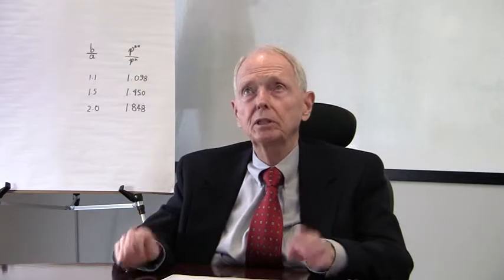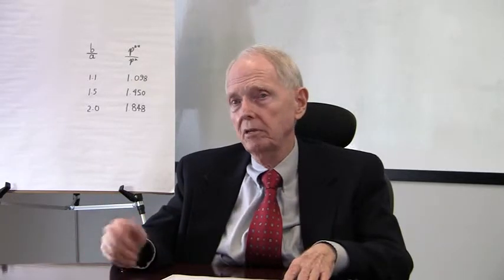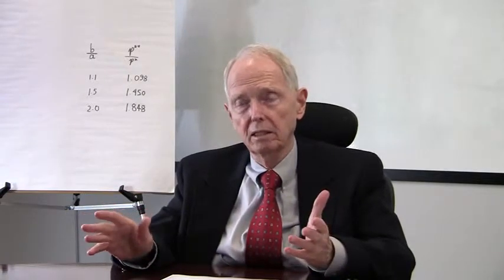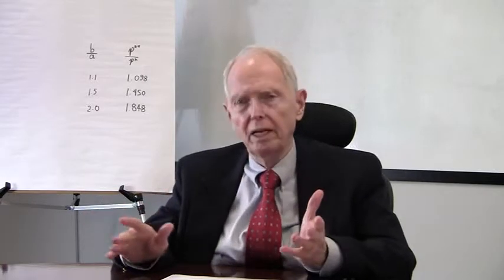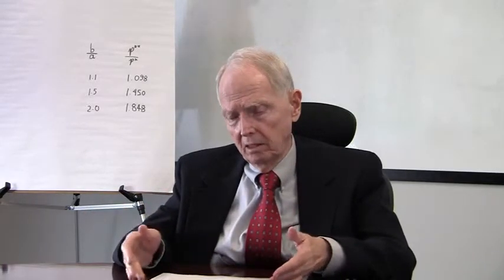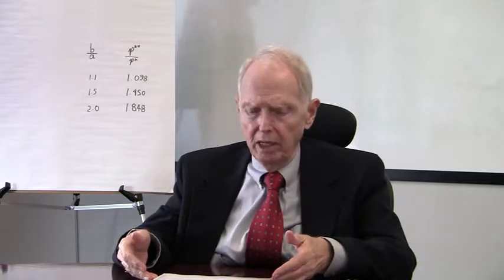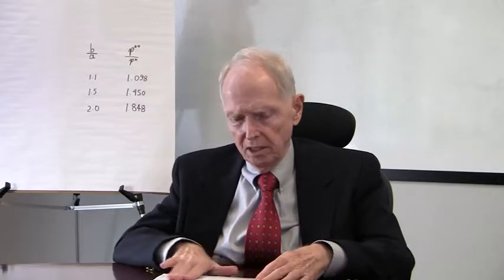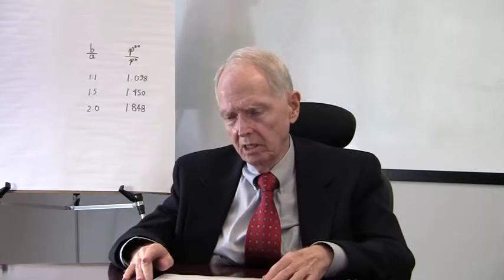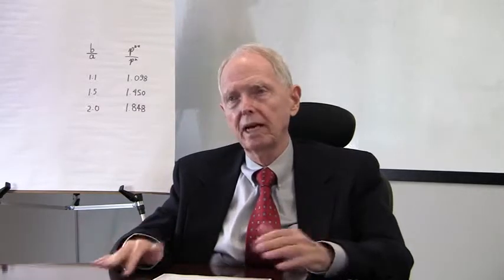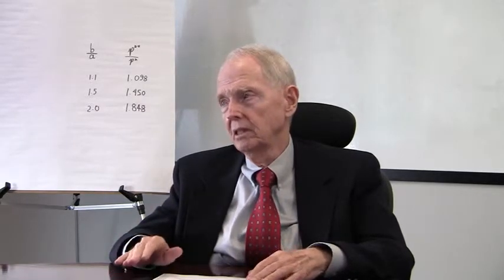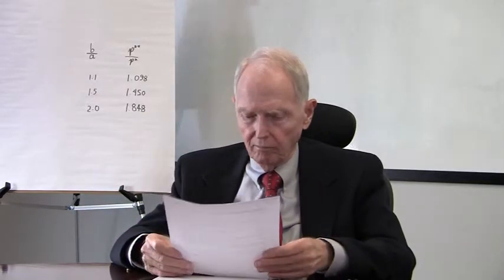So you twist, it starts to yield, and you go another 33% torque before you get to the fully plastic state. And those are numbers that people like to calculate because sometimes that's important. Now on a chunk of metal that you're loading, this number of 4/3 is not atypical. It's the kind of number that you frequently find. Okay, so we'll look at some others later.